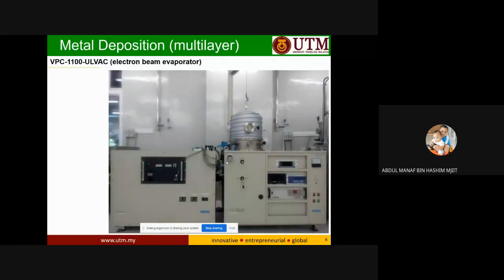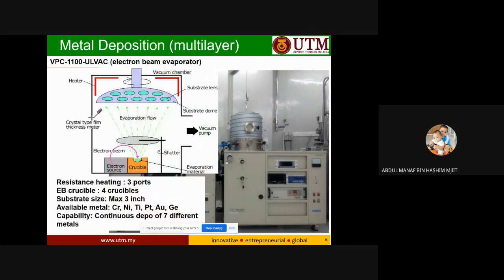Okay, and then we have a metal deposition facility, which is an electron beam evaporator. For this system, for the electron beam crucible, we can put up to 4 crucibles, and in this system we also have resistive heating ports. We have 3 ports, meaning that you can do a continuous deposition of 7 different metals without taking out your sample. The substrate size can be up to a maximum of 3 inches.